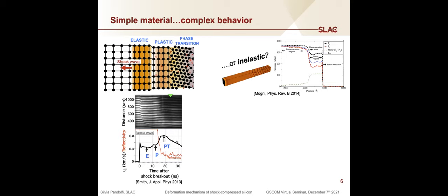However, there have been some theoretical calculations that have suggested that deformation in silicon could happen in a radically different way, which was named inelastic deformation. What we mean by that is that when the elastic wave traverses the sample, there is an imbalance and so a shear stress because of the uniaxial nature of the compression, for which the pressure along the direction of the shockwave propagation is much higher than the one perpendicular to shockwave propagation. And then there is the relaxation towards a more hydrostatic state, in which the pressure is equal in all directions, and so the difference between the pressure along these two directions goes to zero. Classically, this is thought to happen with the generation of defects.